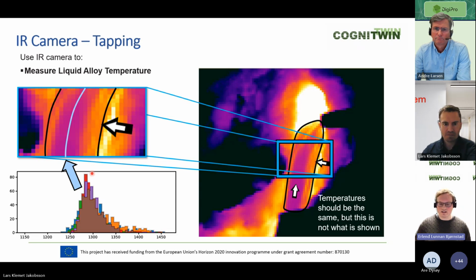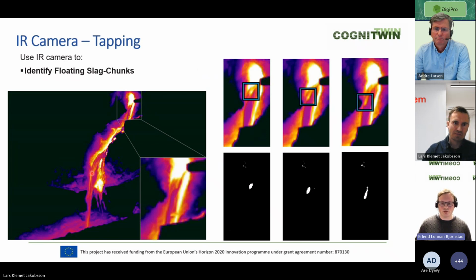Lars, next slide, please. Yeah, so we also want to know something about the slag that comes from the furnace, because that might disturb the chemical reactions that we want to create inside of the ladle. There is this common metallurgical proverb, which is if you take care of the slag, the metal will take care of itself. So here we're trying to understand how much unwanted furnace slag goes into the ladle. Here we are using the difference in emissivity between the slag and the alloy to try to isolate and catch these slag droplets.